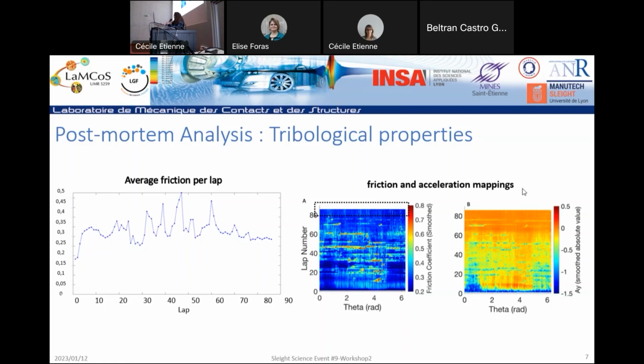So when we see here the red striation, we can't extract information about these events. If we have a striation at the last lap, it's wonderful, we can access this information. But if it's in the middle of the test, we can't have this information on the morphology of the third body. So we conduct different tests at different friction distances to acquire different configurations and information.